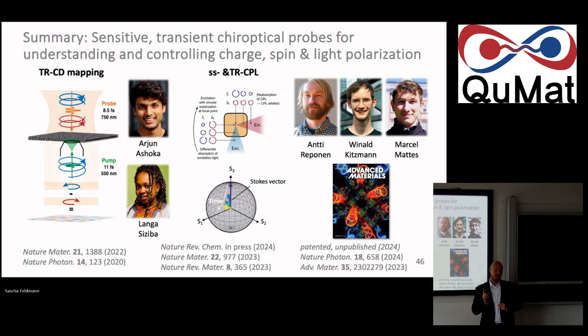But there is hope, because this was a material that wasn't chiral by design, right? This was just a locally perhaps strained and disordered material, polycrystalline, where again we are agnostic to the origin of it. But I have therefore hope that with a by-design made much more distorted crystal structure, we can also really leverage this effect to be much stronger. So skeptical for big Rashba splittings in normal 3D perovskites, except for smaller modulations we picked up here, but hopeful for 2D strongly twisted materials.